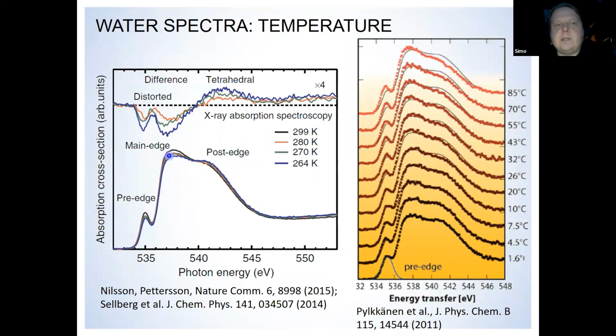And then the main edge typically follows the intensity of the pre-edge, and then the post-edge is typically taken as sensitive to the tetrahedral coordination. An increased level of tetrahedrality in the system means a higher post-edge. You can see these temperature-dependent changes to the spectrum here from a study where the lowest temperature line, measured at 1.6 degrees centigrade, is repeated here as a black line throughout the different temperatures.